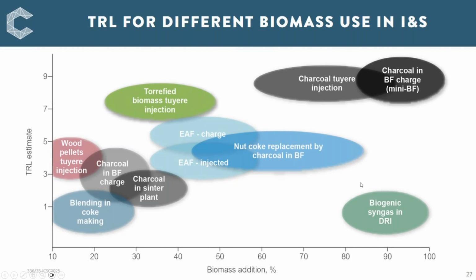So just to point out some of the things I've said, the charcoal addition in the blast furnace, in the mini blast furnaces, has been done at scale, and has displaced 100% coke in a few plants in Brazil. It's been demonstrated there, and also charcoal injected into the base of the blast furnaces. And then on the bottom left, we have processes that are limited in how much biomass they can take. So things like blending biomass in coke making, and it's at a lower TRL. And in the middle, we have adding biomass into the electric arc furnace. Replacing nut coke, which is a smaller sized fraction of coke in the blast furnace, by charcoal, has also been trialled. And then torrefied biomass injection into the blast furnace, which I'll show in a moment.